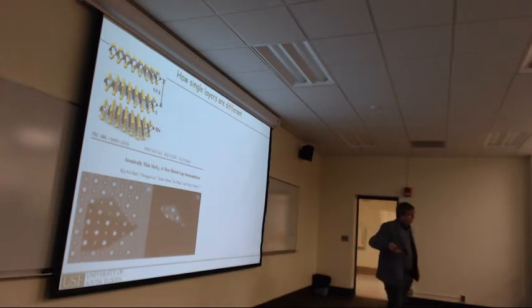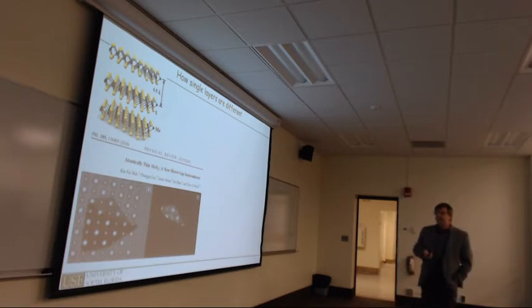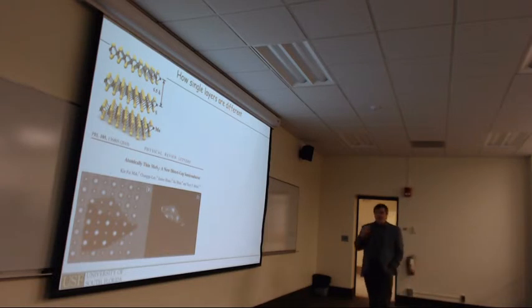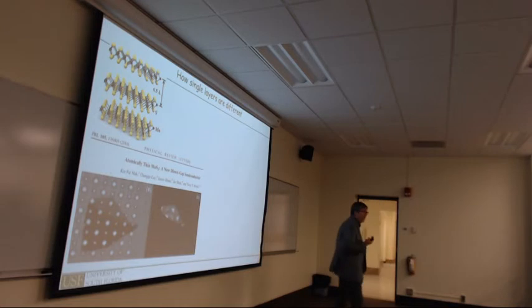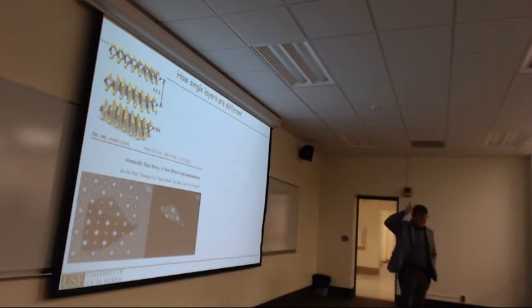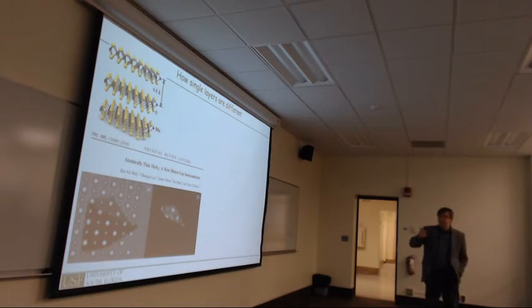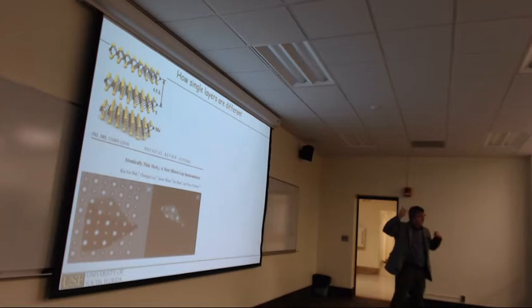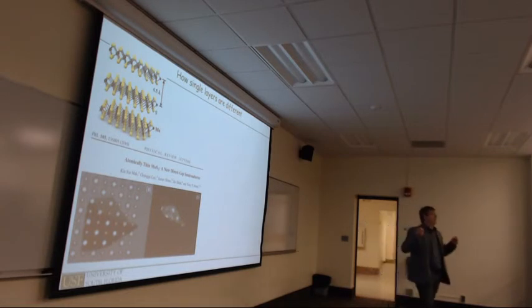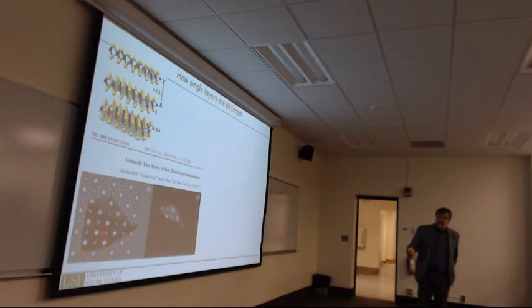Now what's interesting is if you don't look in optical microscopy but in photoluminescence, so you look at the light that comes off the material after you shine light on it, then the bilayer you cannot see at all. There's no light coming off. While the monolayer shows strong photoluminescence. And that kind of photoluminescence is an indication for a direct bandgap material, because here you can have a direct recombination of an electron and a hole, and that gives you strong photoluminescence. While if you have an indirect bandgap material, for recombining an electron and a hole, you need to change the momentum, so a phonon would be involved in that process, and that makes it a far less efficient process. And so the bilayer or multilayer material seems to be an indirect bandgap material.